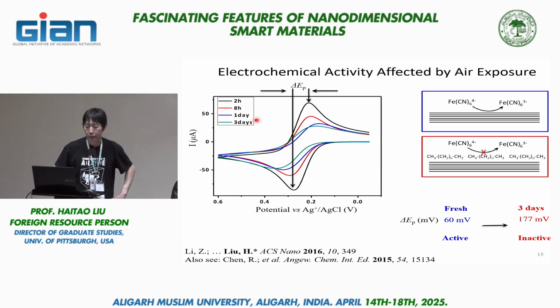However, if you leave the electrode in air for a much longer time, 8 hours, and especially after 3 days, you see two changes. One is that the intensity of the current goes down, so the peak got reduced. But also the oxidation and reduction peak separation increased. And both are classical indications of a more sluggish, slower, or non-reversible electron transfer process.